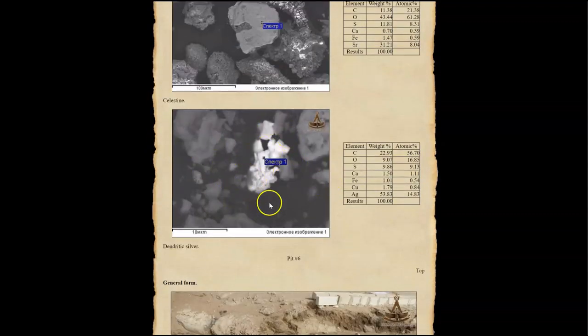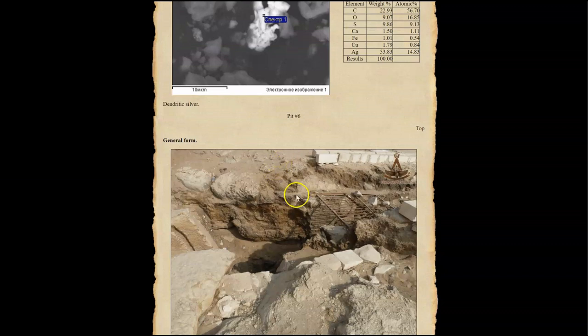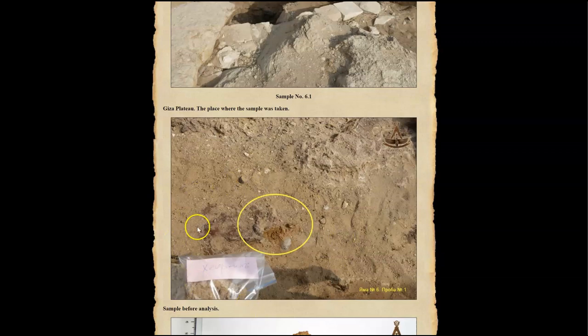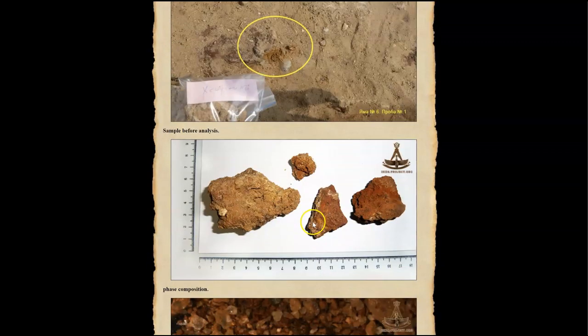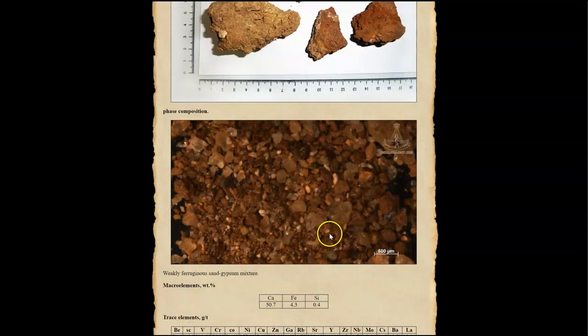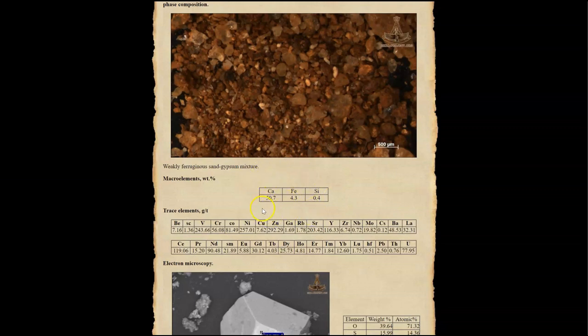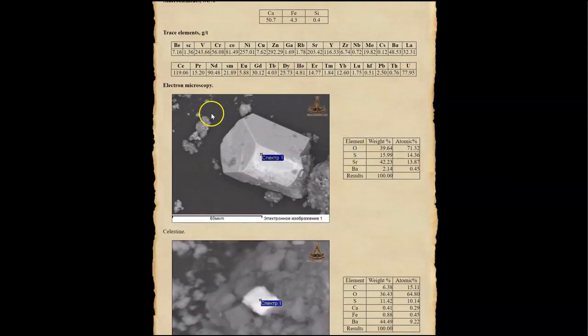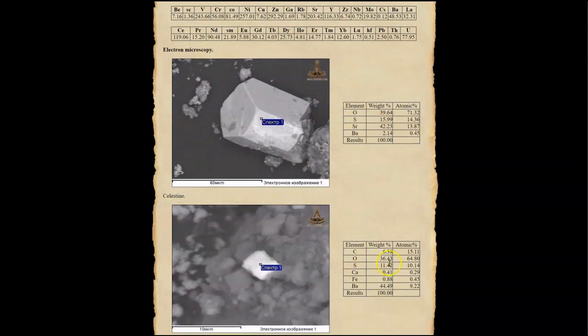And next up, this is some dendritic silver, a microparticle with 53.83% silver, so another very interesting sample at this particular location. And the last one, pit number 6, the location here, an image of the sample location, picture of the material, close up here, and macro element analysis showing 50% calcium, 4% iron, 0.4% silicon. And down here we have some celestine and some barium.